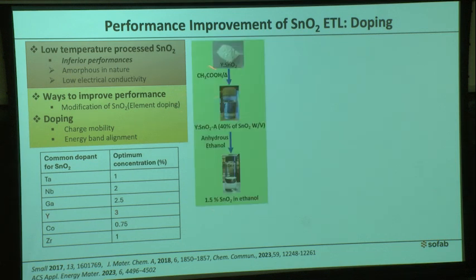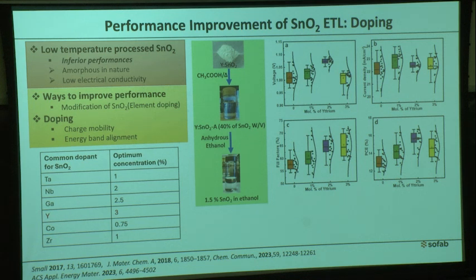We synthesized yttrium doped tin oxide, functionalized it with acetic acid (acetate), and finally diluted this tin oxide. We made a series of flexible perovskite solar cells depositing yttrium doped tin oxide, ranging in concentration from 0 mole to 3 mole.